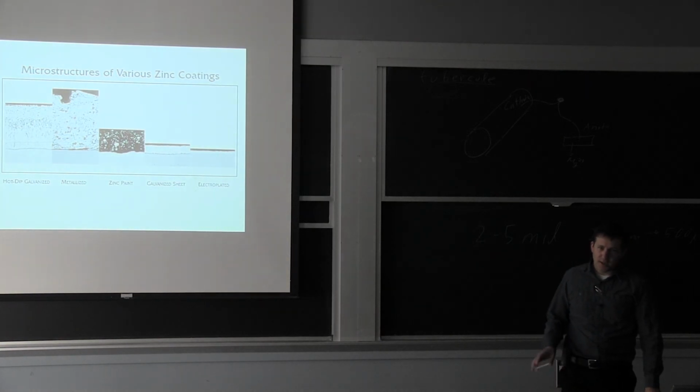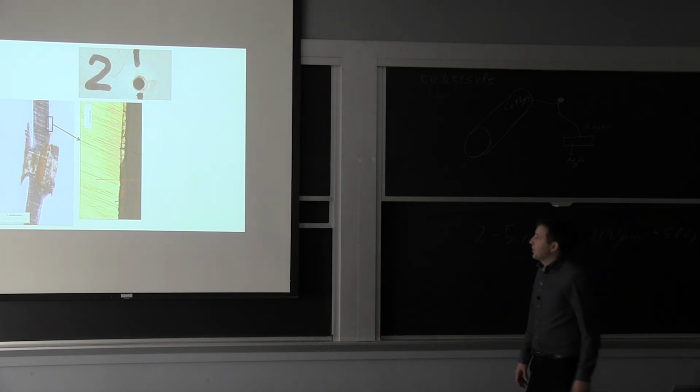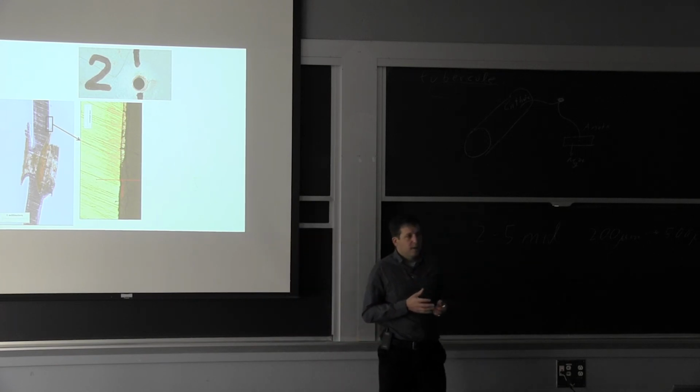If you want high protection, high thicknesses, you talk about hot dip galvanizing, and you may have to specify thicknesses. There are ASTM standards that say, I want 5 mils thickness for this pipe, and that's great. If all you want is minimal atmospheric resistance, then the thinner layer of zinc could be okay, except when you start consuming it.